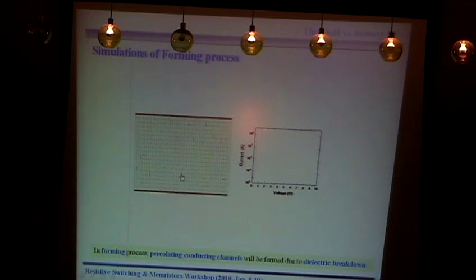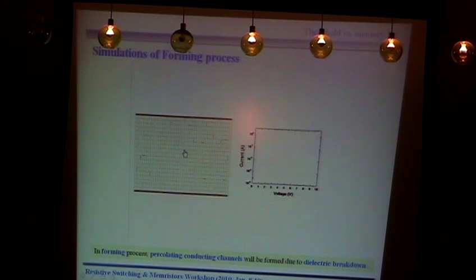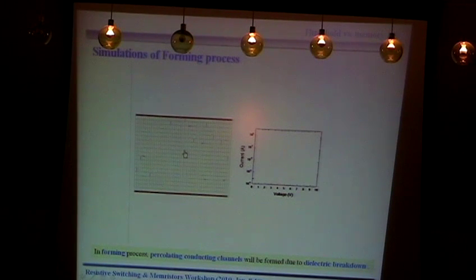But anyway, I will try to show the results of our simulation. We did a simulation with a 20 by 50 square lattice, and we initially assumed that some of the circuit breakers are in the on state. The red in here is the on state, and green is the off state. We also performed the simulation by fixing some of the defects. The initial red line is something like a defect. Sometimes we fix this defect and assume that it does not change, but the result is the same.